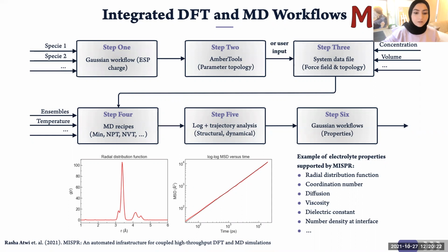The workflows are coupled with analysis codes that we developed for performing different kinds of analysis, like the radial distribution function, viscosity, ionic conductivity, and other properties relevant to the electrolyte. And results from the MD workflow can also be coupled with an additional DFT workflow in order to calculate the properties more accurately by taking the solvation environment that we predict from MD simulations.